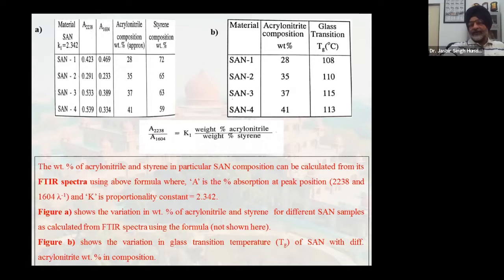And interestingly, we find that with increase in the acrylonitrile composition, the glass transition temperature of the SAN increases. So when the percentage is 28%, glass transition temperature is 108, and it became 113 for 41% composition of acrylonitrile. So you see that same way PAN has pretty high, still higher than this. That is the essential thing we have, because this was checked through differential scanning calorimetric studies. So the peak was occurring at higher and higher temperature for the materials having higher compositions of acrylonitrile.